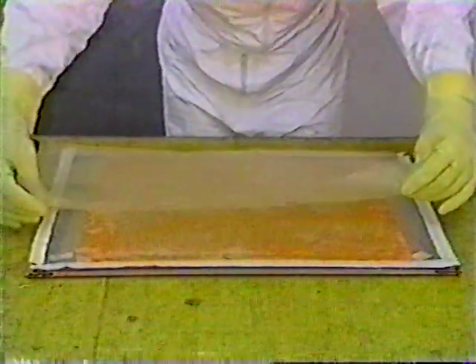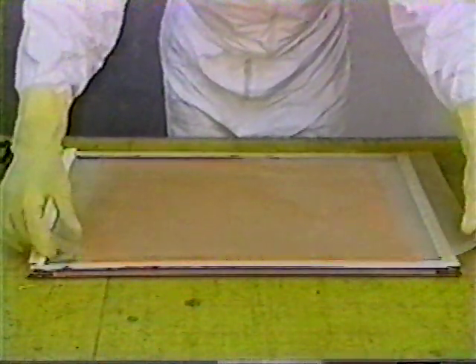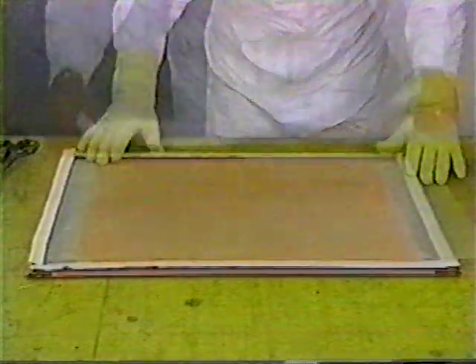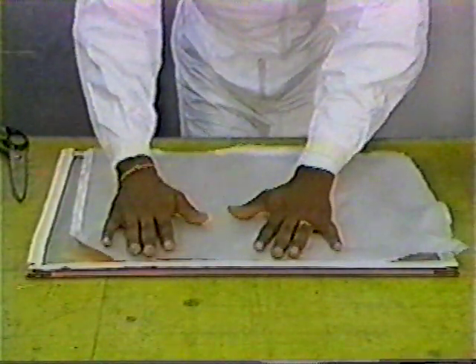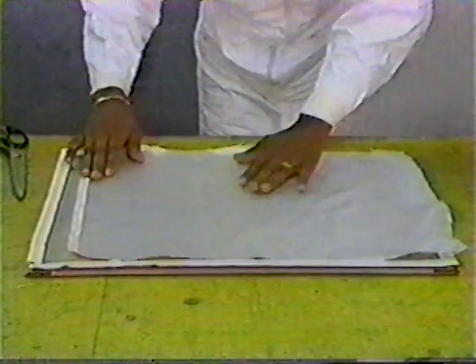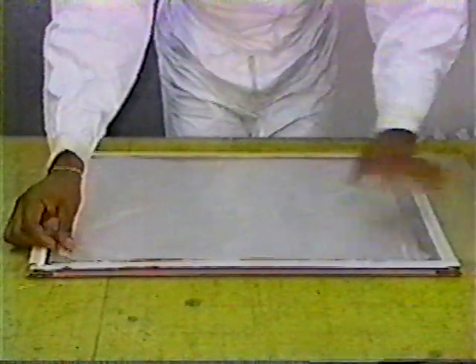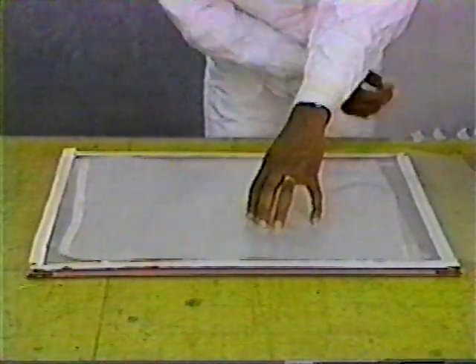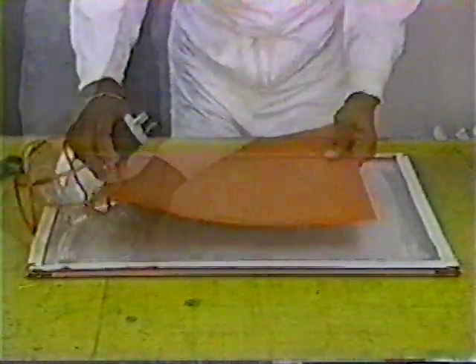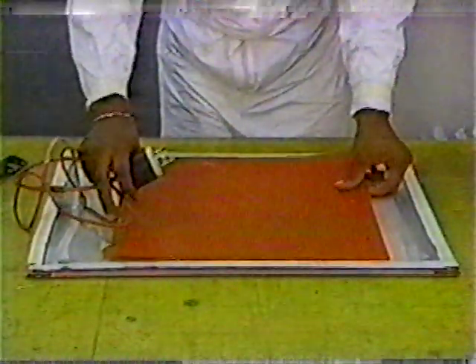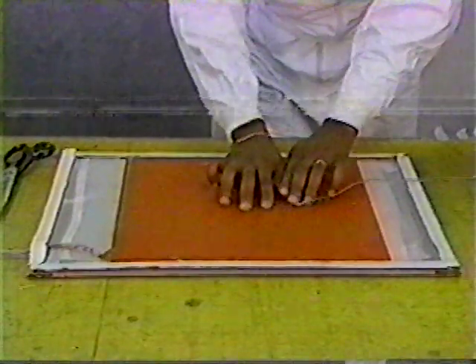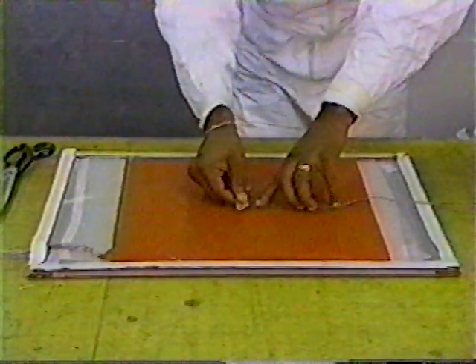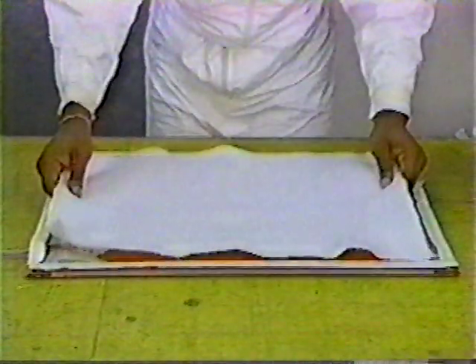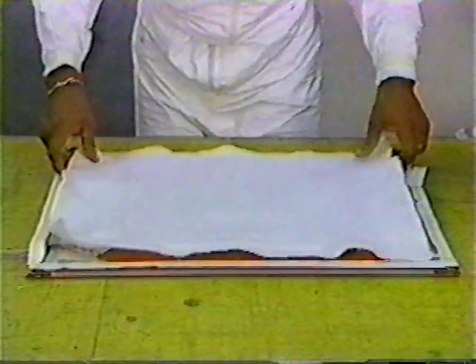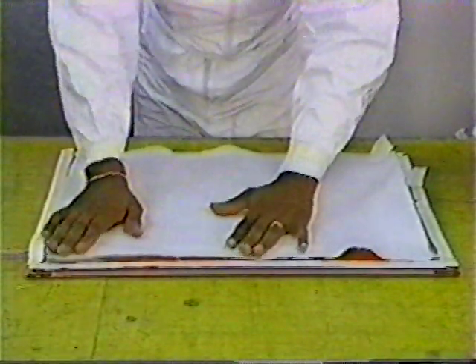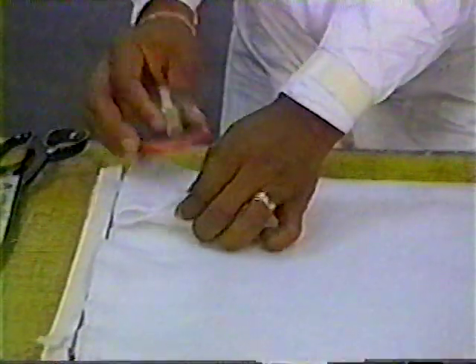Then, place a sheet of porous parting film over the fiberglass stack. This is followed by one sheet of fiberglass bleeder cloth. Next, place a sheet of non-porous parting film over the stack. Then, position the heating blanket. Then install a temperature probe at the center of the heating blanket. Cover this with a sheet of RC 3000 breather cloth. Position a vacuum probe on the breather cloth.